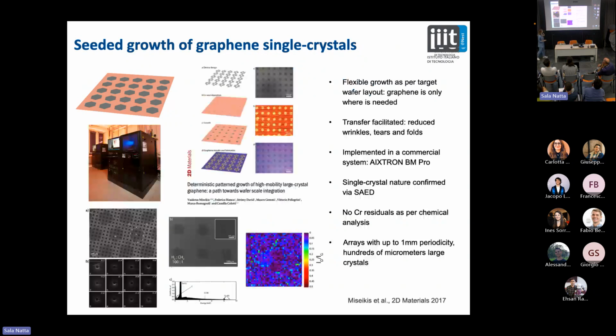It's one of the few times where the practical realization comes out as the idea. So we started to make these hexagons, and another additional interesting thing is that the chromium at the center basically sinks into the metal during the growth. So at the end of the day, you don't have a trace of the chromium on your graphene. So the graphene is good enough for all the CMOS applications and basic applications. If you want to do spintronics and you use magnets, where even having a few atoms of magnetic elements might screw up the entire project, maybe that's not that clean, but it's clean enough, I would say. I mean, you might have a few.